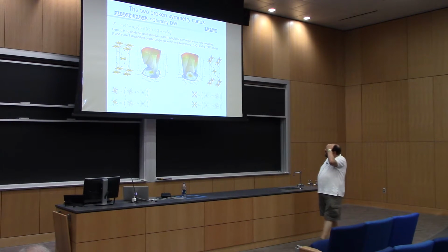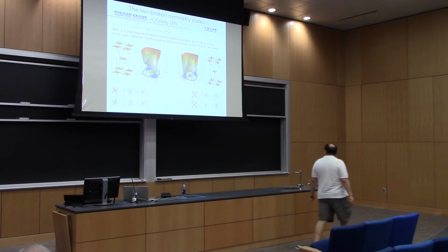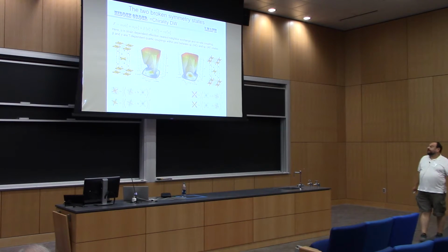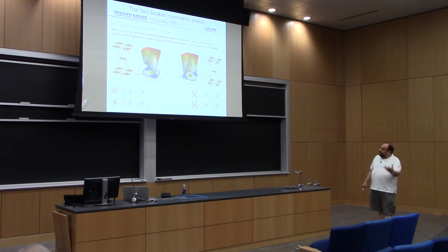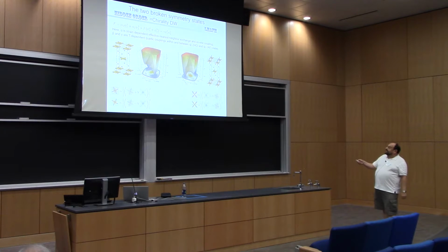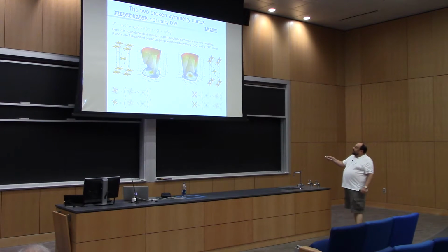Then we have these two competing orders, and we can do quite conventional Ginzburg-Landau. We can present the free energy on the plot of hidden order versus antiferromagnetic order parameter, and we can tune the system from having the lowest state hidden order and an excited state antiferromagnet, or vice versa. So in this case, strain or pressure could be the tuning parameter, and it allows us to drive the system through a first order phase transition, because there is a local barrier there from one state to another.